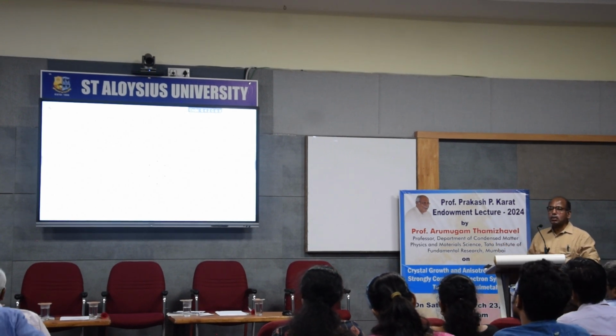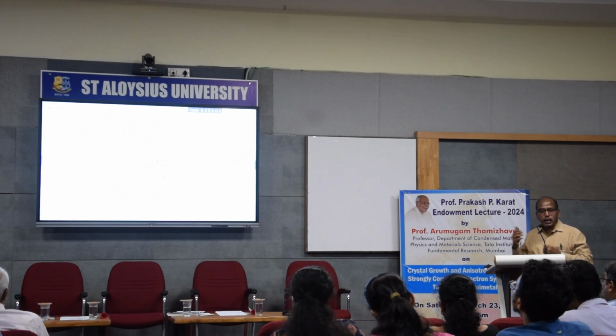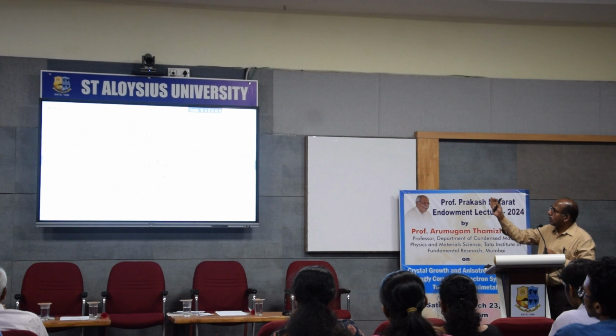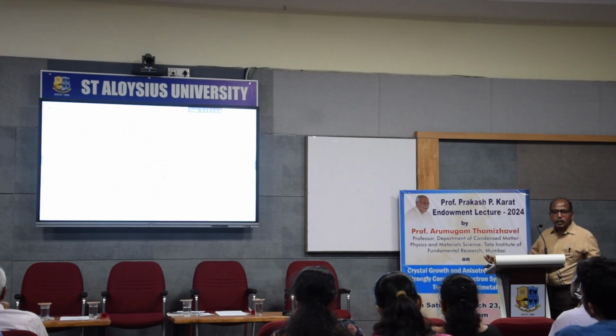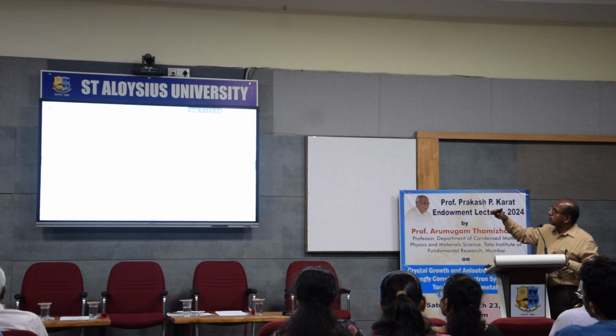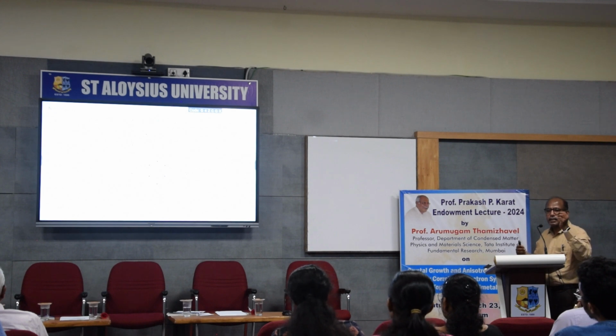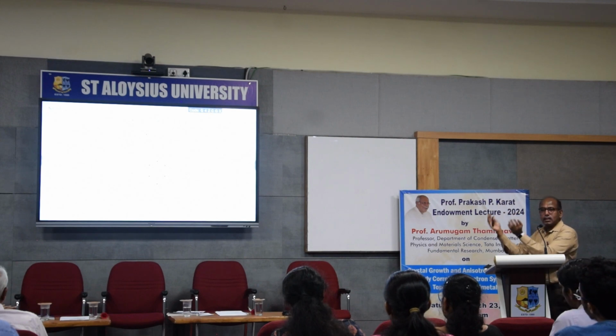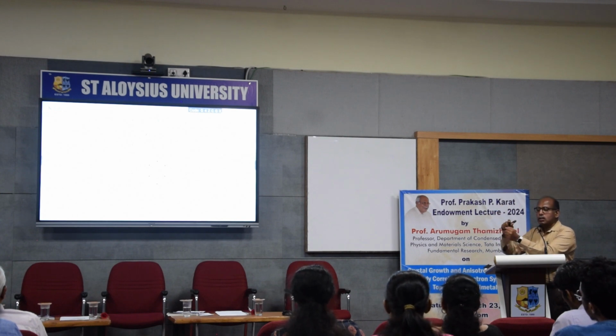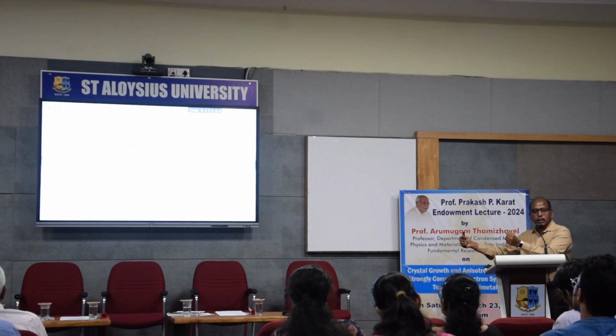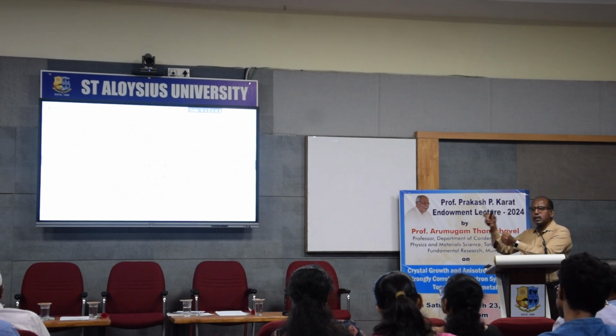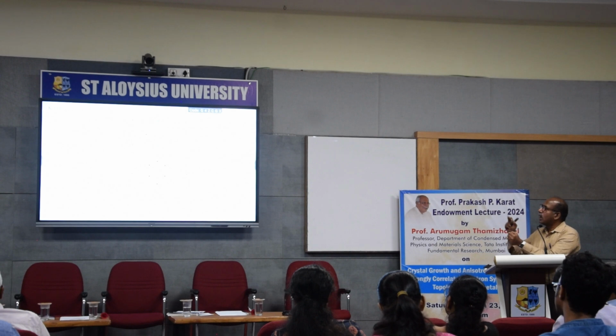And there is another interaction called the Kondo effect. At sufficiently high temperatures, the f electron and the conduction electron don't interact at all. But when you come to a temperature region called the Kondo temperature, the f electron partially interacts, that means they get scattered. At sufficiently low temperature, below the Kondo temperature, the conduction electrons form a screening cloud. There is one f electron, and surrounding it, the conduction electrons are in the opposite direction. So this f electron cannot be seen by another f electron at a far off place. The conduction electrons are screening this f electron, and when this kind of screening happens, you will not see any magnetism.